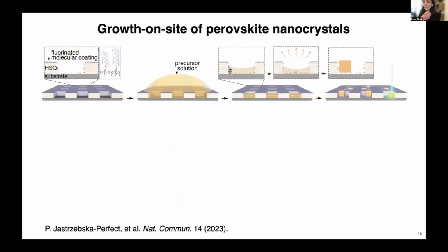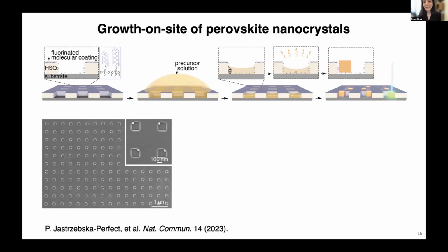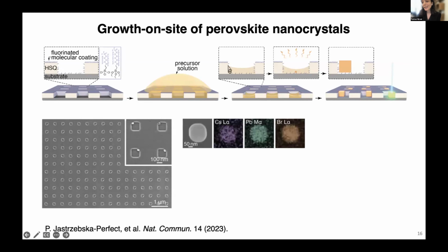So in the approach that we've developed, I won't have time to go through the details, but through changing the surface topography and having asymmetric wettability, we can actually localize the chemical reaction to nanoscale sites over wafer scale. And that allows us to make arrays of these precisely defined nanocrystals, in this case showing you an SEM of cesium lead bromide. Using SEM as well as EDX, we can characterize the structural detail as well as the composition of these materials, just to confirm we have the material that we meant to make.